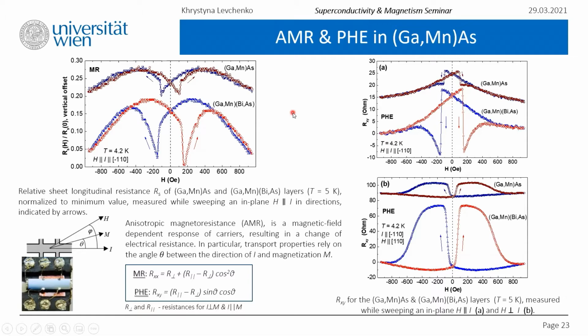Let's just come back for a second to underline a point which will be crucial in a few slides. While we were comparing ternary and quaternary compounds earlier, from the structural point of view, we established that they both have good quality. From the magnetic point of view, they have the same crystalline anisotropy dependent on different buffers with the same set of the magnetization easy axis directions, though some of the parameters, like Curie temperature, were lowered.